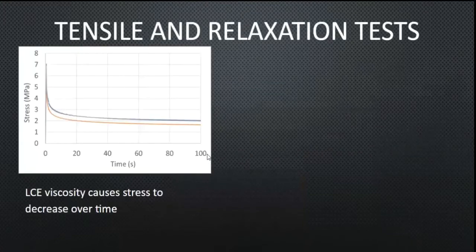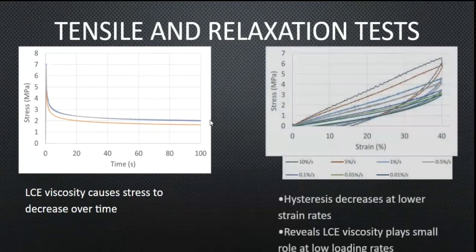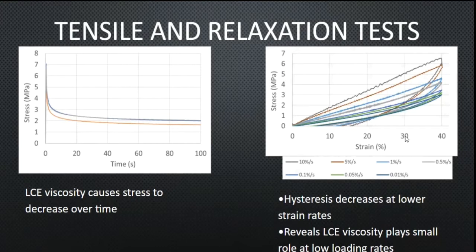For our results, first we have the relaxation test, where you can see that the stress decreases with time. If this were a purely elastic sample, the stress would be a constant value over time because you're keeping the strain constant. But because this is a viscoelastic material, the stress decreases over time — that is the LCE viscosity. LCE viscosity is also seen when you look at the loading and unloading curves. The loading curve for 10% per second comes up to a certain stress level, then unloads back down. The gap between the loading and unloading curves is known as hysteresis, and it occurs because of viscosity. Importantly, at lower strain rates like 0.1% per second, the hysteresis is really small, revealing that LCE viscosity doesn't play much of a role at very low strain rates.